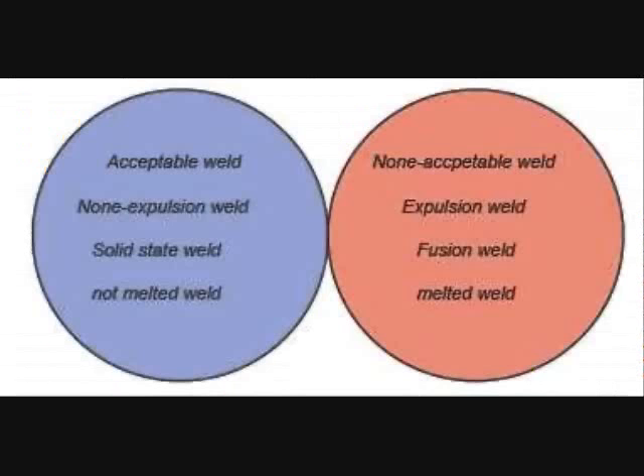Another way to demonstrate there's no way you can weld a non-expulsion fusion weld is to use a Venn diagram. On one side of the Venn diagram we have acceptable weld, non-expulsion weld, solid state weld, not melted weld. On the other side we have non-acceptable weld, expulsion weld, fusion weld, and melted weld. There's no area that can occupy both sides of this circle. So the professors assume you can weld a fusion weld without expulsion. I think that dream will not happen.